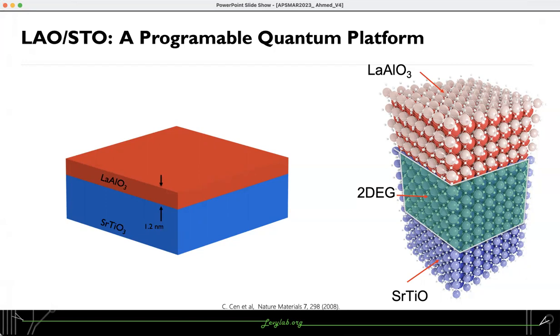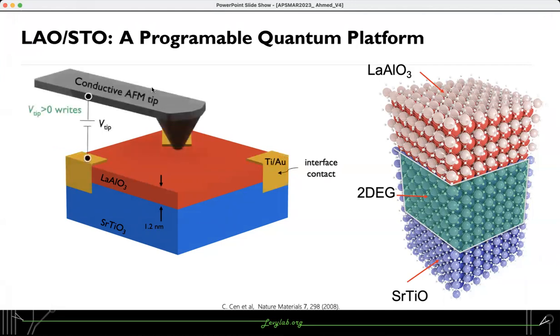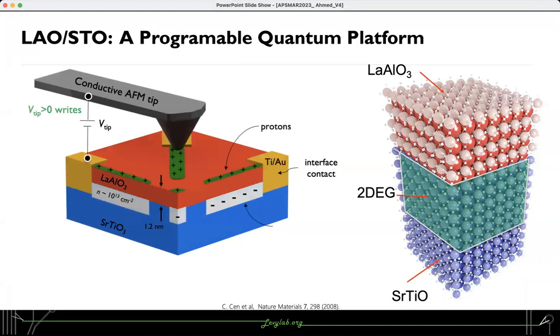conductive AFM lithography. We first create metal electrodes that contact the interface. Then we use a conductive AFM tip that's biased with respect to the interface to sketch the device around. Wherever the tip touches the surface underneath, the surface becomes locally conductive. And this is reversible in the sense that we can change the sign of the voltage and reverse back to an insulating phase. Using this technique, we can create lots of interesting quantum devices with very high spatial resolution.